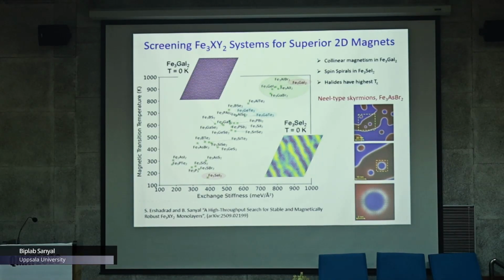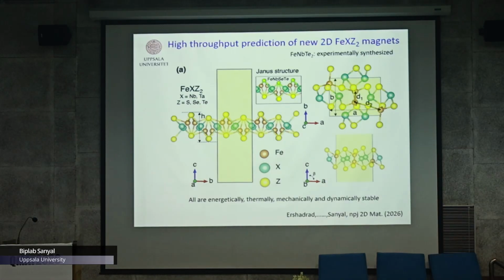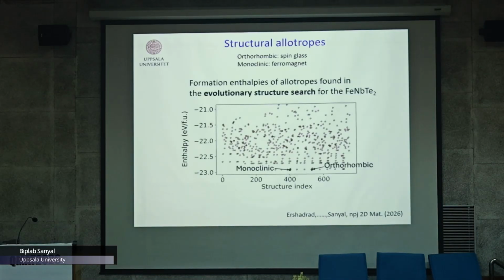And then to see whether these properties can be studied. And in the last 2 minutes, we also looked into another type of chemical composition, iron XZ2, following this particular material, iron niobium tellurium 2. This niobium comes from the 4d series with high spin orbit coupling and things like that. So we wanted to study what happens if we replace this niobium by other elements, for example tantalum, and these chalcogens can be sulfur, selenium, and tellurium. All this combination of materials pass the stability criteria. So that means we can go and look into the magnetic studies. Nevertheless, one small point is that this particular material actually crystallizes in two structures, orthorhombic and monoclinic. Orthorhombic shows a spin glass phase, and monoclinic shows a ferromagnetic phase. So we concentrated on that.